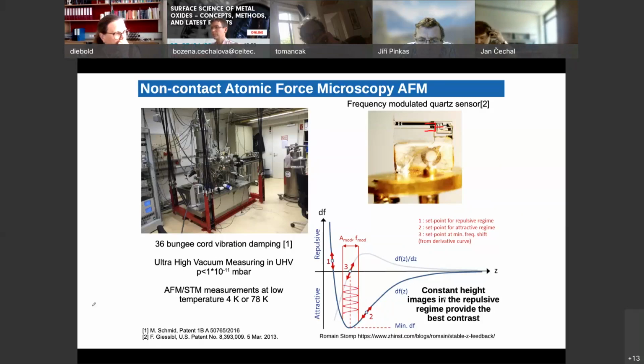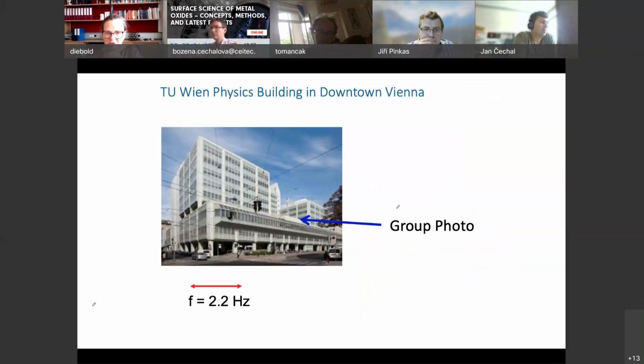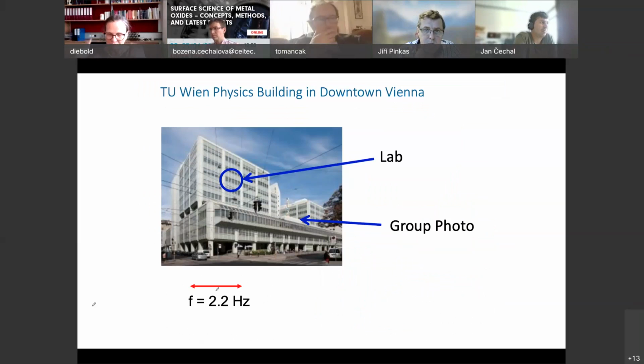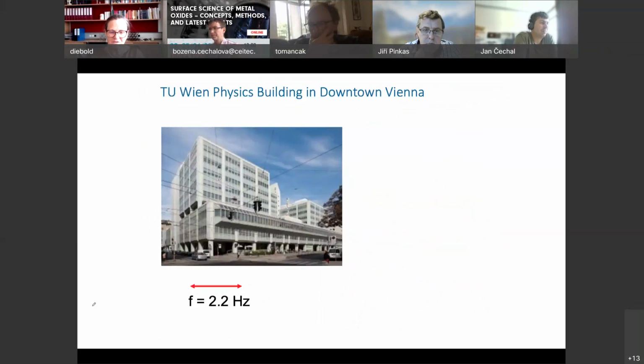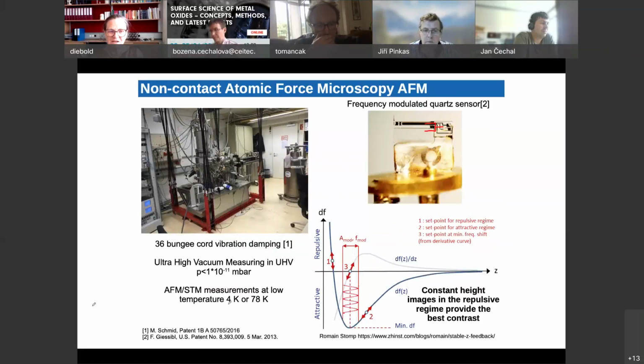Now, all these images are done in constant height mode. That's why we have mounted the whole chamber on these bungee cords, because this is where the group photo was taken, I showed in the beginning, and this is where our lab is. The whole building swings with 2.2 hertz with an amplitude of a few microns. So we have to decouple the whole instrument from the building. That's done with these bungee cords. And the measurement is done at low temperature, at 4 Kelvin or 78 Kelvin.